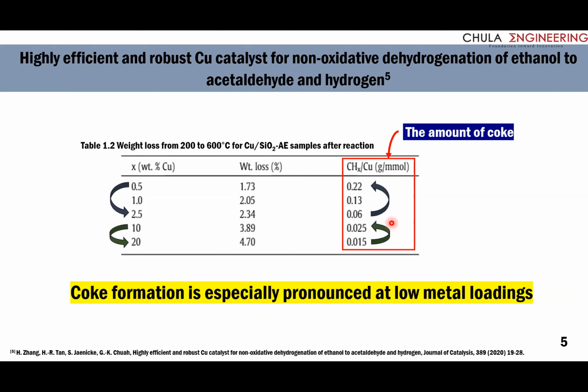For 500 hours, using 10 and 20% weight copper silicon dioxide AE respectively. In comparison, much higher values were found for this one, 0.5 to 2.5% weight copper silicon dioxide after only a few hours on stream. Thus, it can be concluded that coke formation is especially pronounced at low metal loading.